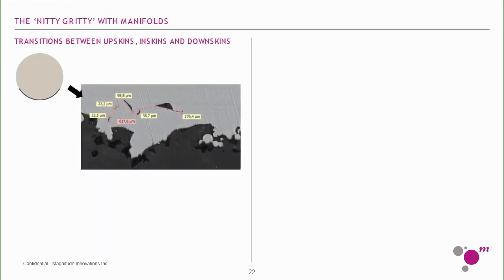The next thing that we look at is, after defining the entire volume of the part, we take a look at the surfaces. Now, in a typical laser powder bed fusion process, when you take a look at downskin areas, you have completely different parameters from the vertical walls and the upper facing walls. And those kinds of parameters lead to these kinds of defects. These defects are actually subsurface porosity that occurs in the process because the layer is at too steep of an angle.